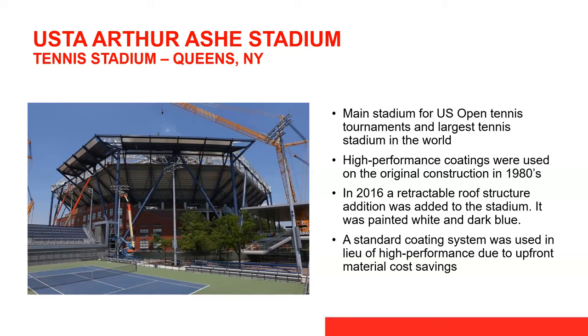It was painted white and dark blue. And a standard coating system was used in lieu of high performance due to upfront material cost savings. So a three-coat system was specified: a zinc, an epoxy, and a urethane. And then there was a discussion about warranty. And so an FEVE fluoropolymer was recommended as the top coat so that you could get the longest term color and gloss retention for the project. And as mentioned, it was value engineered out basically due to cost, and a standard system was included.